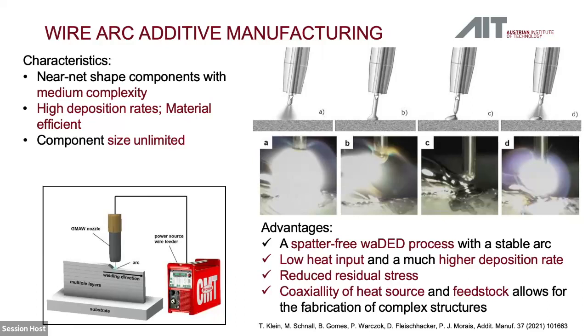In this variant of the process, it's called cold metal transfer, that is shown here, the sequence. It's using a consumable electrode where the arc is ignited between the electrode and the substrate. Here you can see the burning arc. That arc forms a droplet on the tip of the wire. Once this is formed, the wire moves forward and deposits this droplet into the melt pool. When this is happening, a short circuit is formed, and only once the wire is retracted, the arc reignites and the process starts anew. This sequence happens with 70 Hertz. So this is the way we are building up structures.